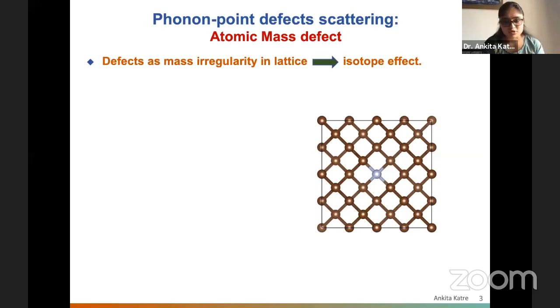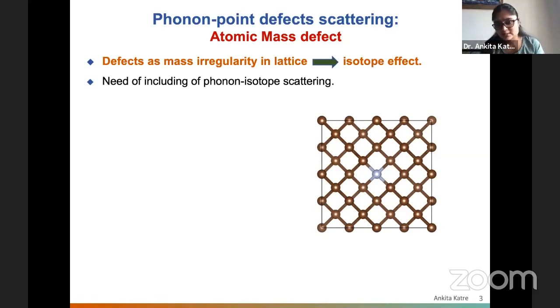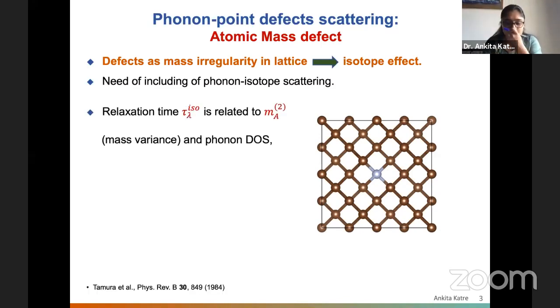We can work in this approximation and see how much good thermal conductivity prediction we can make with it. So this is basically what we'll call phonon isotope scattering, because it's just the mass difference and nothing else is different. So we'll just consider it as mass difference isotope scattering. And I'll tell you later that we use this formulation for the isotope scattering only. Now, this formulation was worked out by Shinichiro Tamura in 1984, and it's quite famous.